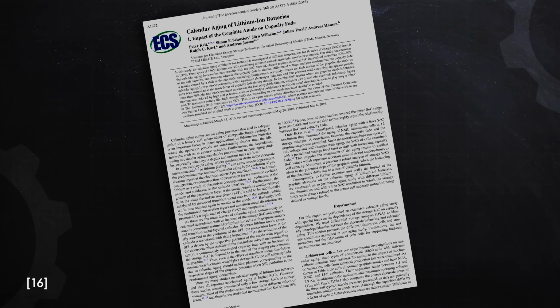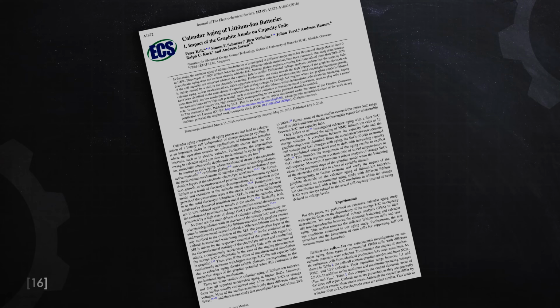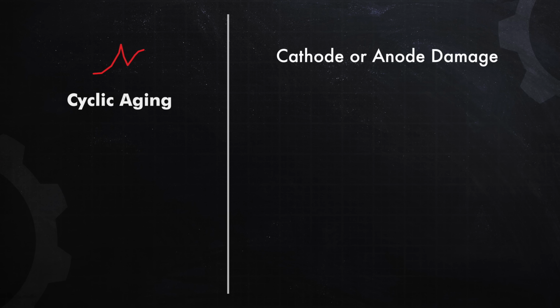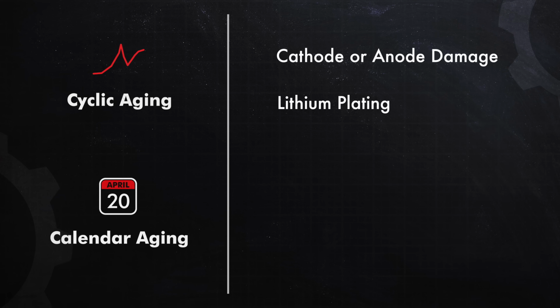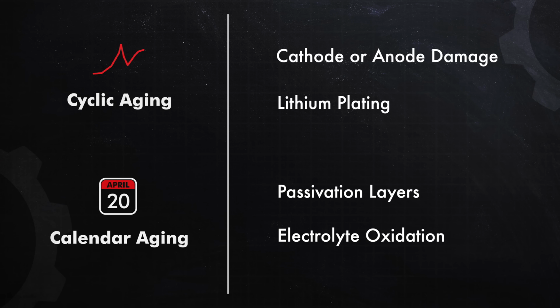When it comes to cyclic aging, a paper by Keil and others suggests that there are two main mechanisms that are responsible: cathode or anode damage and lithium plating. Looking at calendar aging, there's also two mechanisms: passivation layers and electrolyte oxidation. These are the four most prominent mechanisms. I say most prominent because the internal workings and degradation mechanisms of a lithium-ion cell are very complex, much more complex than I currently understand or have time to get into today.